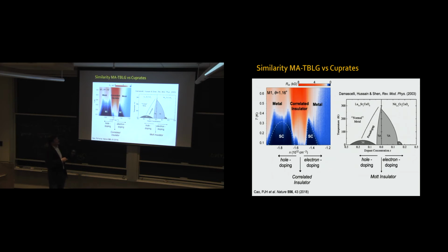The difference is that in order to plot this phase diagram, each point on the x-axis is a different chemical growth, a different crystal, and typically a different material class, because not all materials can be grown across all doping ranges for electrons and holes. So you have to grow thousands of materials, literally, to do this. Here, I go from here to here in 10 seconds with my voltage knob, in a single material with a single disorder realization. That gives us a lot of tunability and flexibility.